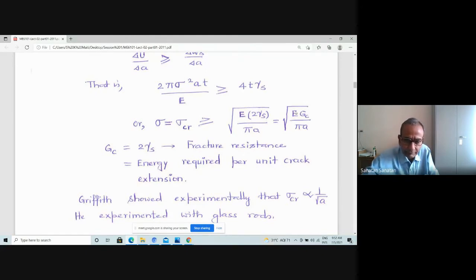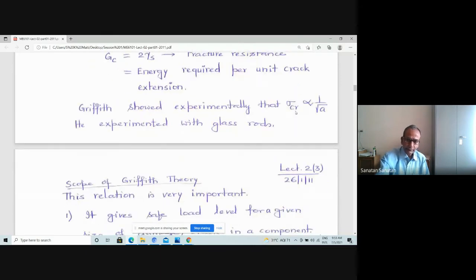Griffith, in fact, showed experimentally. He did experiments, and nobody will believe without experiment. In science, you cannot just propound a theory and have people accept it. You must also show it experimentally. And therefore, Griffith did experiments, and finally he showed that sigma C is proportional to 1 by root A. So that's the reciprocal relationship. He did many experiments with glass rods, and then finally said that whatever the theory says is what comes up. So that's how it became the starting point of finding out the critical load capacity of a structure in the presence of a crack. It is a fantastic stage of development of strength of materials or material science.